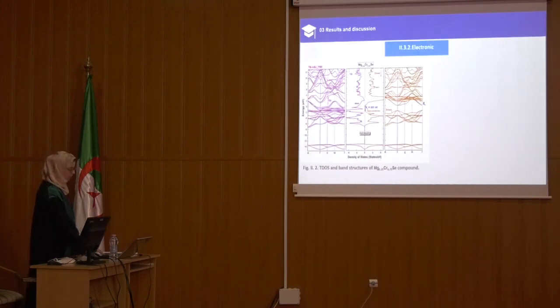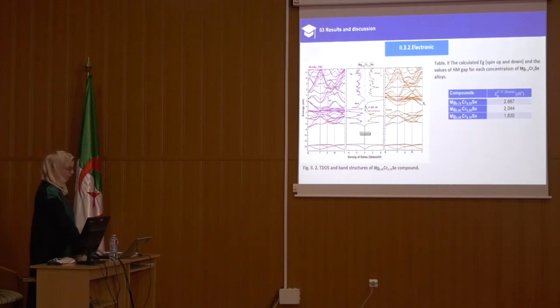For the concentration of 0.75, we observe the same behavior, a half-metallic character, and the calculated band gap values are presented in table 2. We can see that as the concentration increases, the band gap decreases.